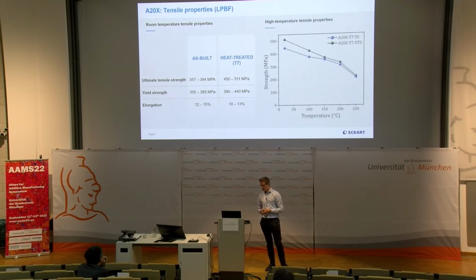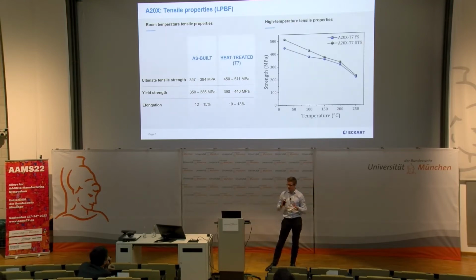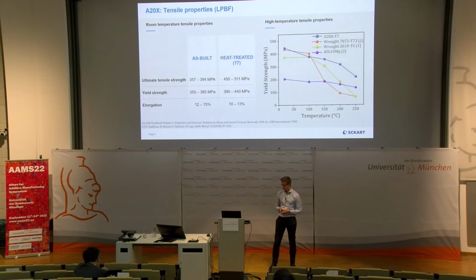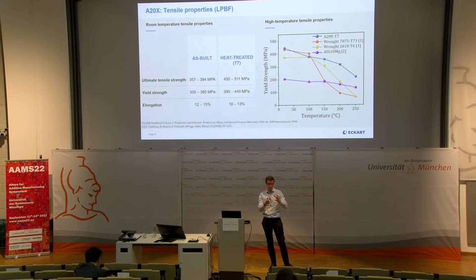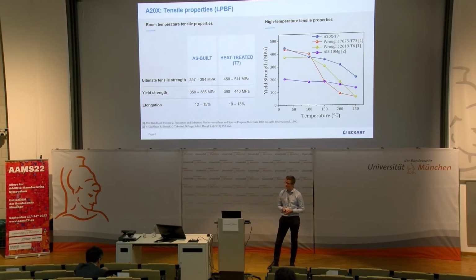Shown on the right is the effect of testing temperature on UTS and yield strength. At 200 degrees C, the yield strength is still above 300 megapascal. To put this into perspective, these are typical competitors. If we're looking at aerospace materials, this is what we're looking at, the benchmarks.